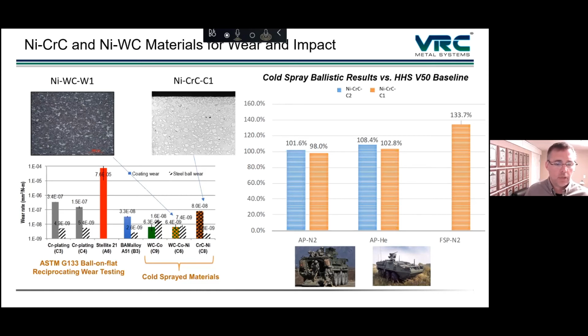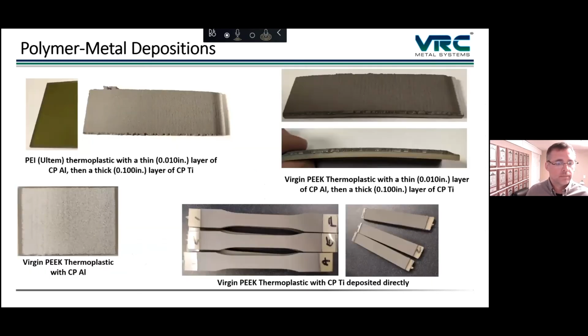We're about on par when we use nitrogen, but even with nitrogen, when you start to look at fragmentation rounds, which is all the way over on the right, we're seeing actually a significant improvement in the performance there. So with armor piercing rounds, we're on par when we spray with nitrogen, but with fragmentation type rounds, we've actually improved over what the baseline steel was capable of. It's also possible to spray metals onto polymers and also polymers onto polymers and so forth. Again, anything that has plasticity in it, we can spray, and we can combine a lot of different materials together.